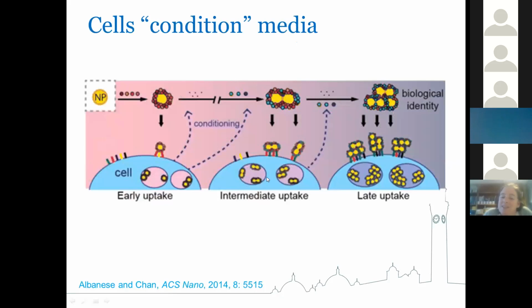So then they were suggesting that there might be a difference in the uptake of these intermediate particles, and then over longer times it might be even a different process. So it could well be that the initial particles are taken up by one receptor mediated process, whereas later on a different receptor mediated process is utilized because the particles have a different identity. And that's not something that's been taken into consideration really in standard testing or in how we go about understanding the longer term distribution of nanomedicines, for example, or the longer term toxicity of particles.